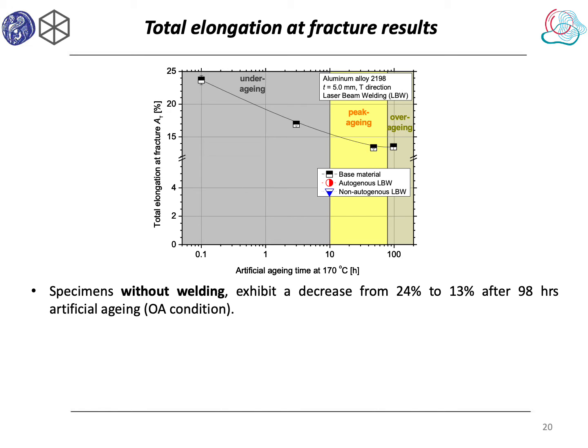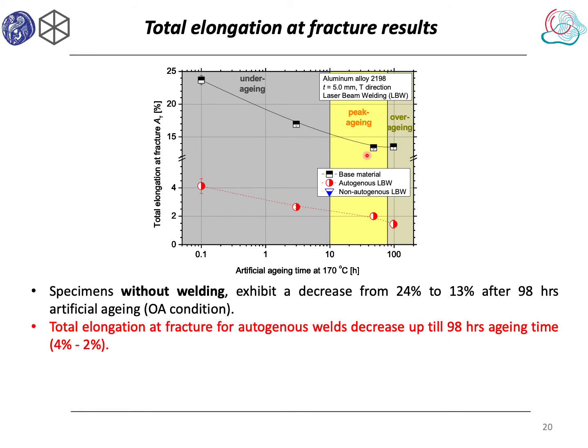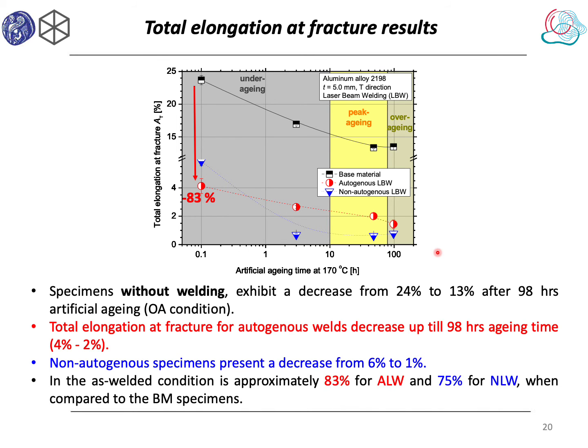Total elongation at fracture, with increasing artificial aging time, for the base material presents a decrease from 24% to 13%. Autogenous welds show a decrease from 4% to 2%, while non-autogenous specimens present a decrease from 6% to 1%. For example, in the as-welded condition there is approximately an 83% decrease for autogenous welds and 75% for non-autogenous when compared to the base material specimens.